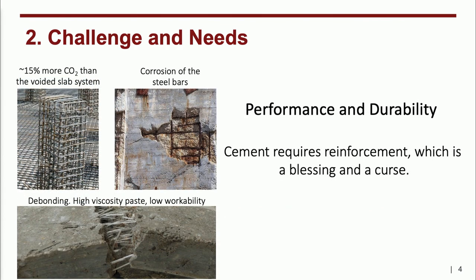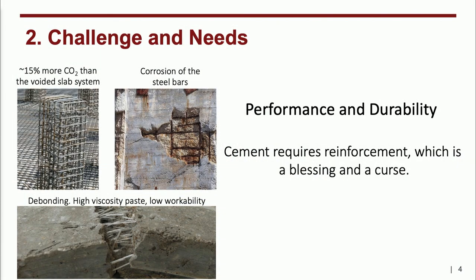The second challenge and need is that cement is a great material, but it has one flaw. The flaw is that it needs reinforcement because the tensile strength is low. And reinforcement is really a blessing and a curse, because it's good, but at the same time, as Leora just mentioned, the stainless steel used for rebars creates even more emissions. The second thing is that rebars are responsible for the corrosion of concrete, which then creates spalling. We can also think of reinforcing the cement at a lower scale by using fibers that are added to the slurry. However, because the fibers have a different composition with respect to the matrix, the materials normally experience what is called debonding, or fiber pull-out.